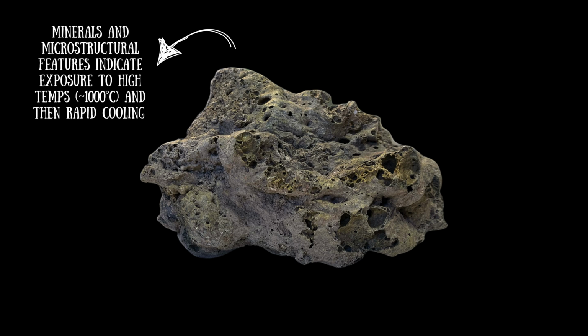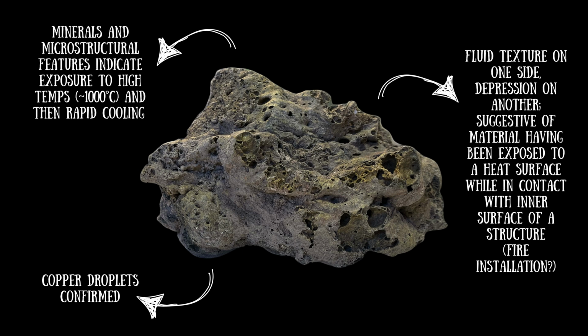What exactly did the researchers find? First, the finding of certain minerals, like tridymite, and microstructural features, such as calcite crystals, revealed that the material had been exposed to very high temperatures of around 1,000 degrees Celsius and then rapidly cooled. Second, they identified small droplets of copper within the vitrified soil lump, confirming that molten copper was mixed in with the soil and thus indicating that the metal, either in native form or originating from an ore, was exposed to high temperatures. Meanwhile, the fluid texture on one side of the lump and a depression on the other together suggest that this vitrified material was exposed to a heat source while in contact with a structure's inner surface. This strongly suggests that it was not only exposed to very high temperatures, but that this exposure took place in a controlled environment, in some sort of fire installation, hinting at deliberate pyrometallurgical experimentation.